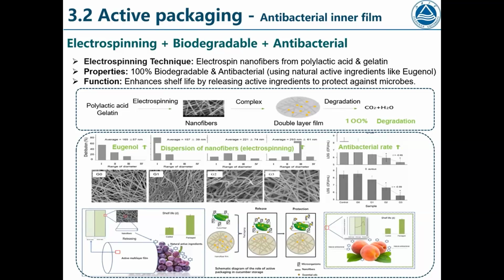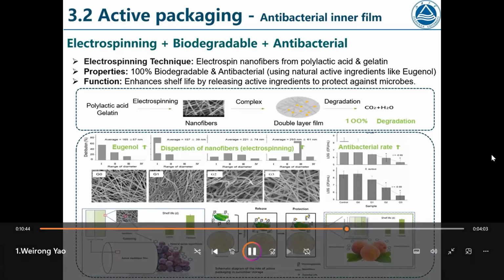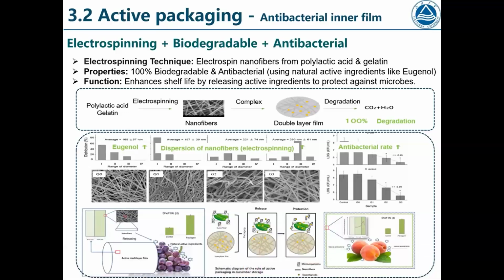We demonstrated their higher antibacterial rate against common pathogens like E. coli. Then we used this active film to package grape, cucumber, or peach, all showing a significantly enhanced shelf life, more than 30% to 50%.